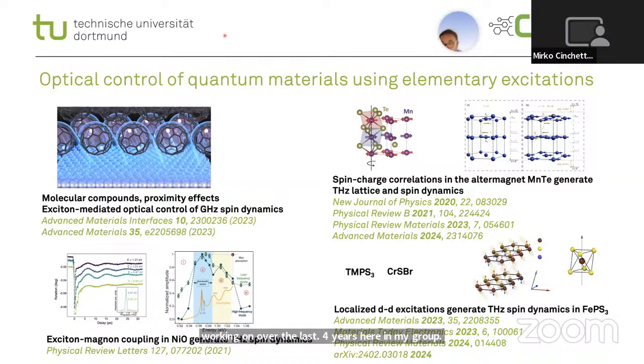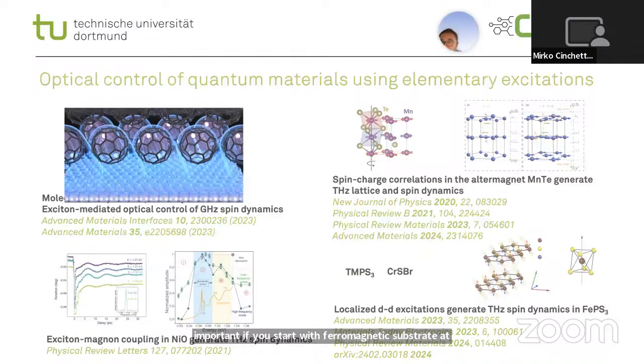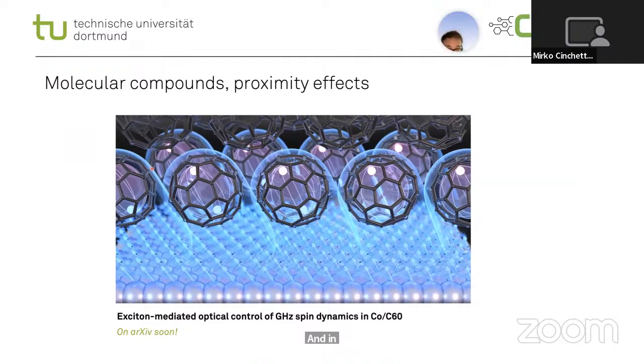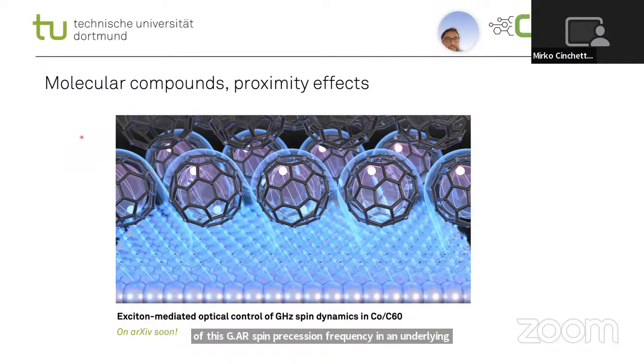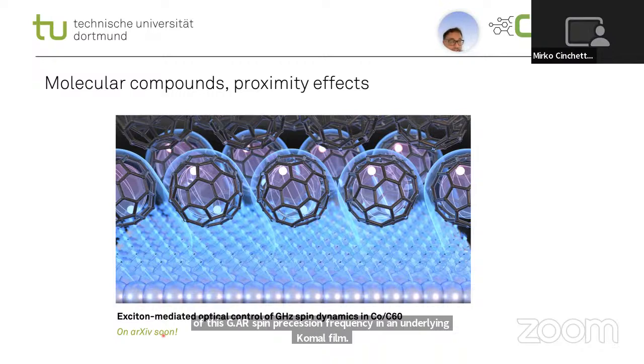So one intriguing possibility to achieve this goal is to exploit proximity effects. And it turns out that these proximity effects are particularly strong and important if you start with a ferromagnetic substrate and deposit a molecular layer on top. In fact, recently we have been able to demonstrate that the extreme optical tunability of C60 molecules can be used to achieve a 60% modification of this gigahertz spin precession frequency in an underlying cobalt film. We are putting this on the arXiv soon, and we will also present this work at the Ultrafast Magnetism Conference in September if you are interested.